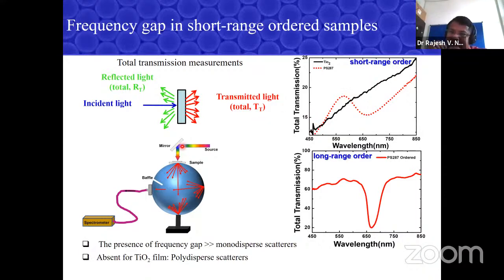But when we do it for the other sample, which has correlated scatterers or short range order, we see there is a dip in the transmission spectrum. It's not a monotonous decrease just like a powder. And initially we got quite worried because we thought we were making some mistake. I'm talking of the year 2017-18, but later we understood that no, it is correct, because this resonance or dip is happening because of the short range order, and this has to happen because there is a local ordering present in that. And if you make the same sample using a long range ordered structure, just like the photonic crystal I talked about, you can see that the gap is preserved in a much better way, because here background is not a big issue since there's not much disorder, but in this one the background is quite bad because there's a lot of multiple scattering happening.